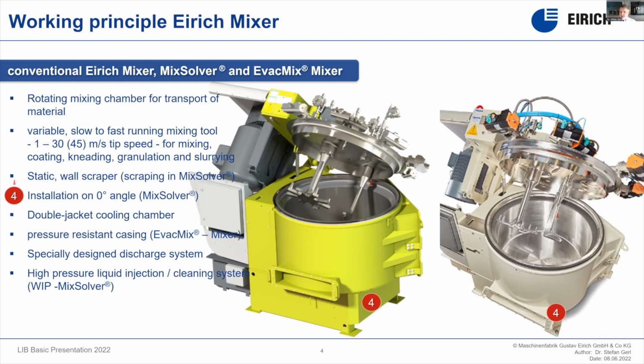The original mixers were all horizontal. In the 70s, Eirich started to incline the machines. So if you have a look onto our webpage, you see lots of machines with a 20 or 30 degree inclination. But for the battery application, we moved back to the horizontal. First of all, a liquid will not flow up the hill while moving. Secondly, the cohesiveness of these ultrafine powders typically forms a wavy material flow inside of the machine. And with the horizontal machine, we can make sure that we have an even distribution and no problems with material leakage out of the machine at any point.